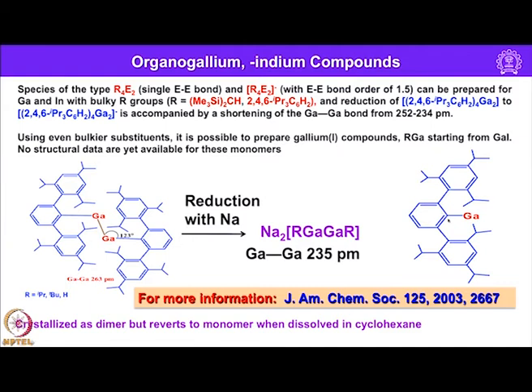So, if you use sufficiently very bulky groups like this, you should be able to make an alkyl gallium having alkyl to gallium ratio 1:1. So, this one undergoes dimerization, and this one on treatment with sodium undergoes reduction to form a gallium double bonded compound. Here gallium distance is 235. This is an indication of the multiple bond character between gallium and gallium. Of course, for more information one can look into this paper, appeared in JACS in 2003. So, this crystallized as dimer but reverts to monomer when dissolved in cyclohexane.